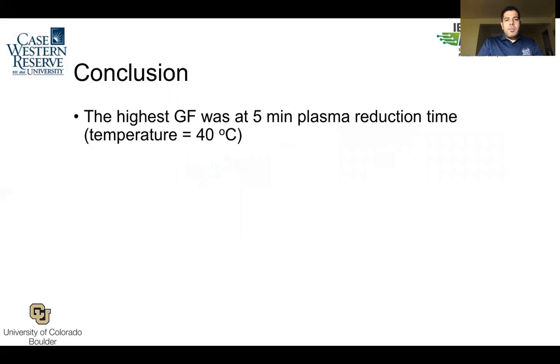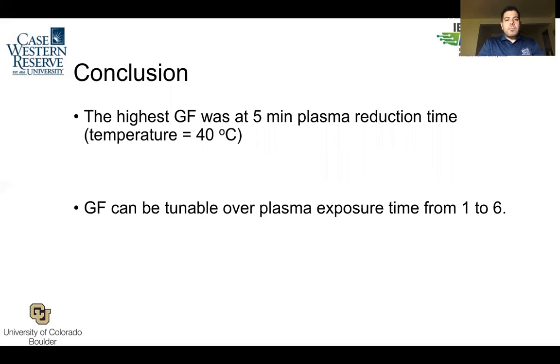In conclusion, I have to say the highest gauge factor we obtained was at 5 minutes when the sintering temperature was at 40 degrees Celsius, about 6. The gauge factor is tunable over plasma exposure from 1 to 6. And since we did cyclic testing, we showed that our sample showed good repeatability over 20 cycles. This concludes my presentation.